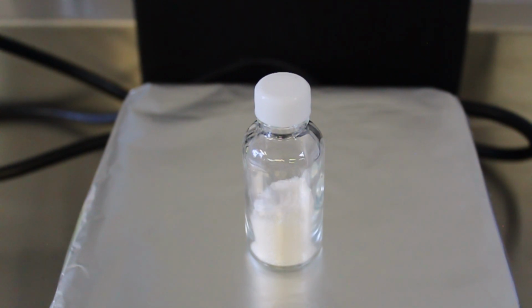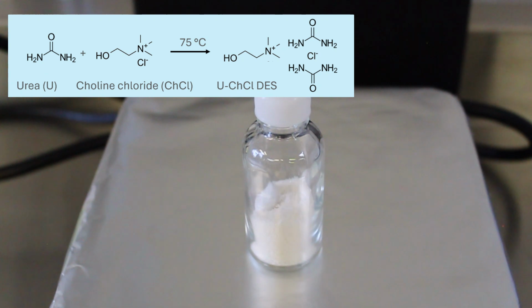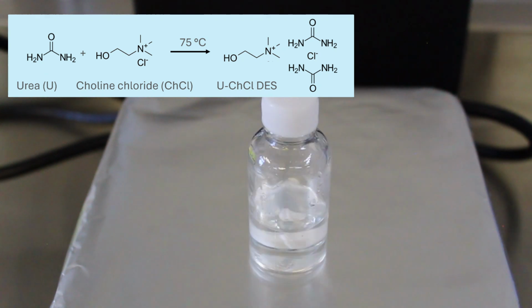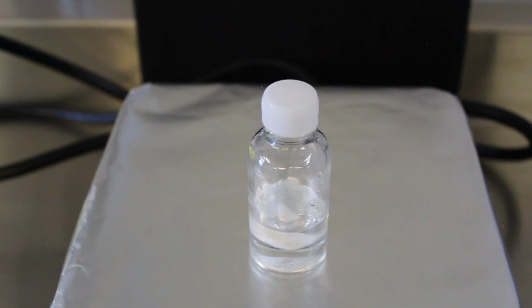In this work, we used a deep eutectic solvent made of choline chloride urea as media for the synthesis of metallic colloids through a chemical reduction methodology using ascorbic acid. This deep eutectic solvent has proven to modify the size, morphology, and crystallinity of nanostructures, resulting from structure-directing properties and viscosity, as a consequence from the speciation of its components and their hydrogen bond network when in liquid state.